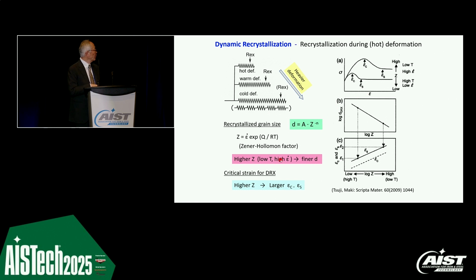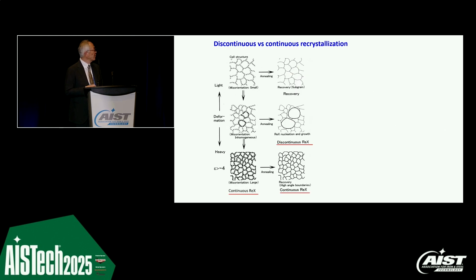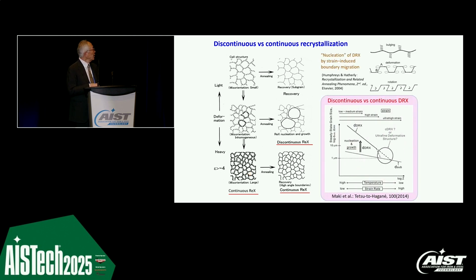So although we can obtain ultrafine grain materials, we need to apply heavier deformation. So that's why severe plastic deformation is very important now. Also, there's a discussion about the recrystallization phenomena from discontinuous one to continuous one. By applying further strain, up to the severe plastic deformation level, the subgrain structure changes to the ultrafine grain structure by increasing grain misorientations by absorbing the dislocation at the grain boundary. And dynamic recrystallization, of course, as given in the textbook, we can have the subgrain for continuous one, particularly the subgrain change to the high angle grain boundary.